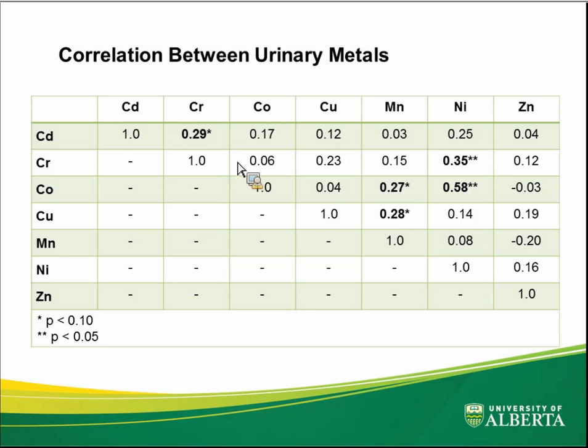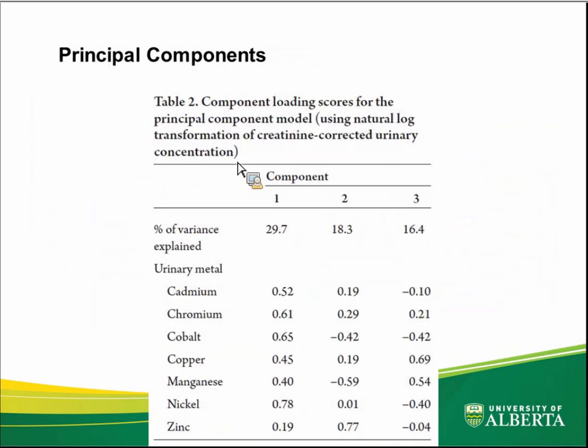And so we then looked at how the metals were related to each other. And so we looked at correlation coefficients. These are Pearson correlation coefficients for all the metals. And we see that there are a few significant associations, but not drastically high correlations between these metals. The highest is 0.58 between cobalt and nickel, and really the rest fall below that. But we used, as I said, the principal components analysis to look at whether groups of these metals could be used to better identify exposure patterns.